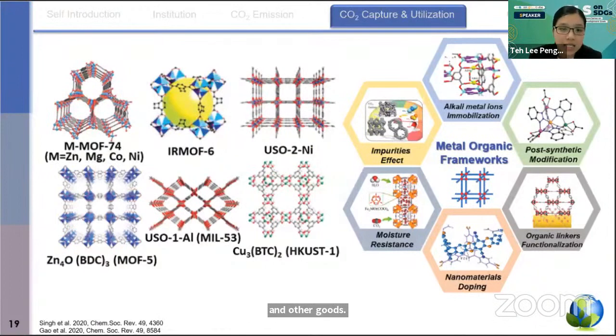CO2 adsorbent is MOF materials. MOF material is currently very popular due to its high surface area, and we can easily tune the pore of the adsorbents. Then we can do different kinds of modifications and functionalization of the MOF to enhance the CO2 adsorption capacity.